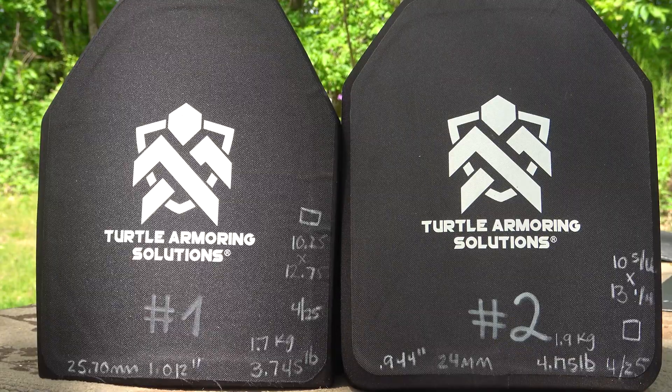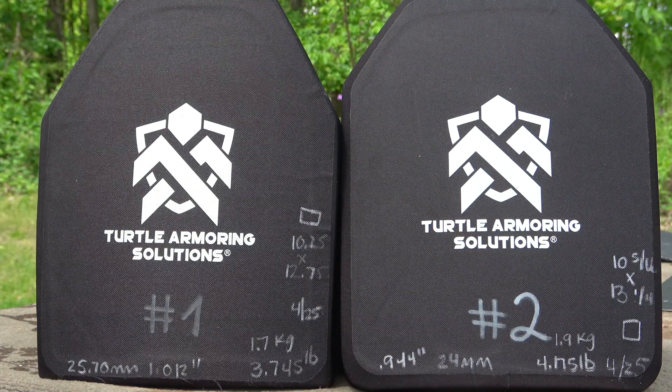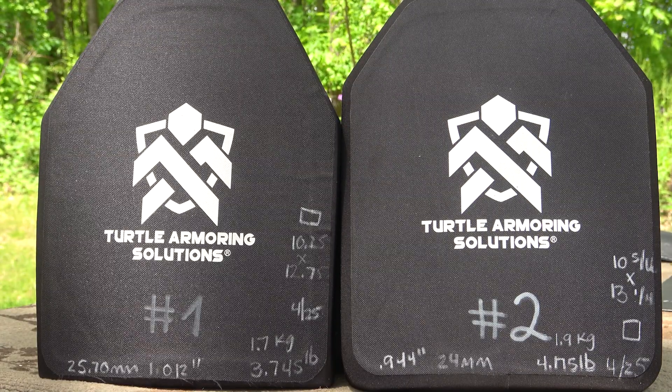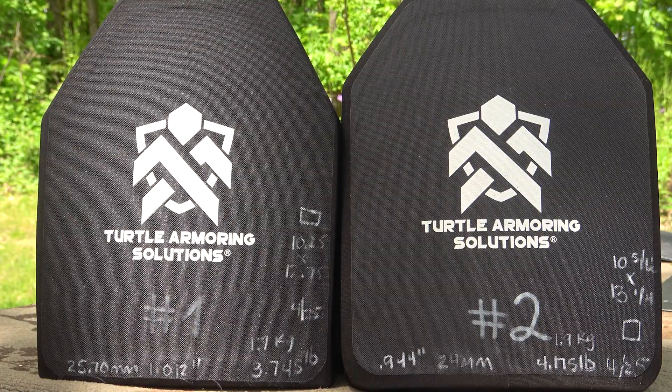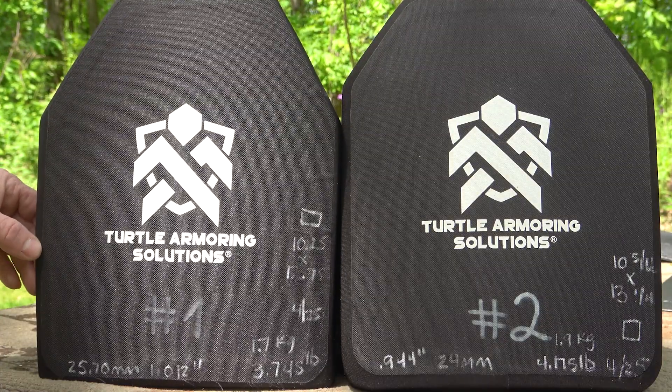If you see something like 60 to 70 millimeters in my clay, in the NIJ's eyes that would be failing. Since this plate is 100% through-and-through ultra-high molecular weight polyethylene, there is no need to drop it on its face two times as a pre-conditioning test per NIJ standards. And since it's 100% pure polyethylene, there is no concern about the strike face going out to the entire edge of the plate. I can feel that it is fairly rigid out there.